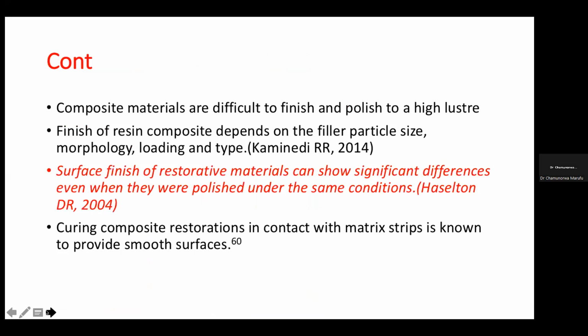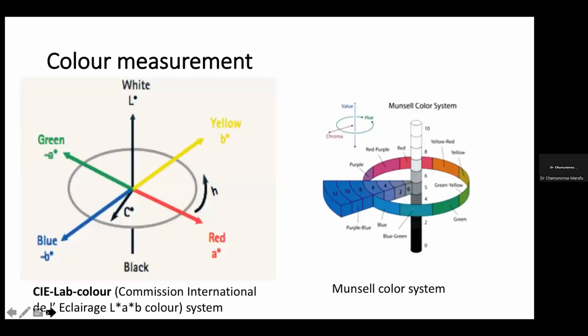And then because of their nature, being composed of a resin and inorganic fillers, composites are difficult to finish and polish to a high luster. The finish of these restorations depends on the filler type, particle size, morphology, and loading and type. Though one study by Haselton reported that even when finished in exactly the same way, these composite restorations would sometimes have significant differences in the finish. And curing composite restoration in contact with a mylar strip is known to provide the smoothest finish.